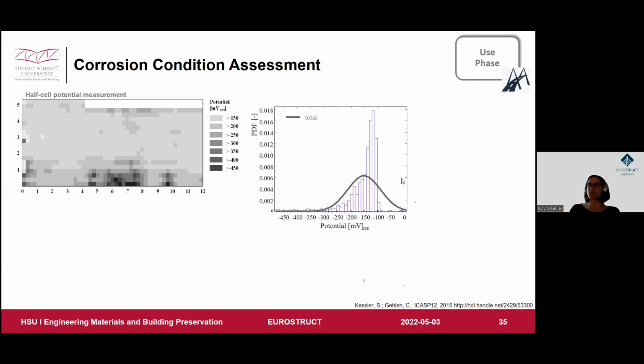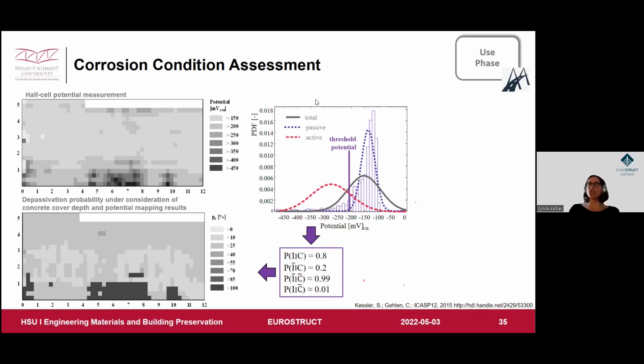We can also work further with the real data, which we see here. We do some statistical analysis, and here I do not want to go into detail too much. This is also published in the conference paper you see beneath. Later on, we are able to transfer the half-cell potential measurement directly into a corrosion probability. So this is a failure probability, a corrosion probability. Now you really get a clue. You have a quantitative evaluation of the corrosion condition assessment of your structure. You can easily see where you have a really high corrosion probability, about 80%, and which parts do not show a corrosion indication at all. And with these data, you can really work for further inspection, and for further repair, and you have quantitative values.